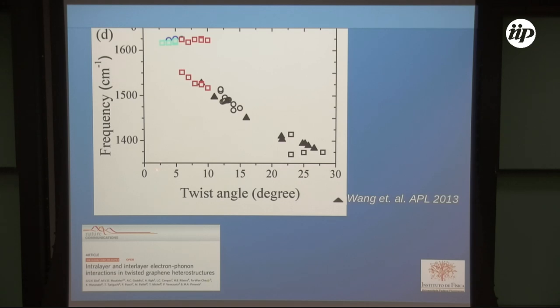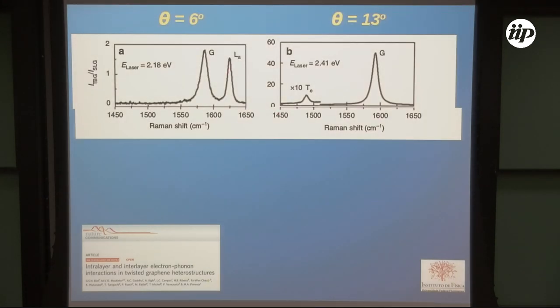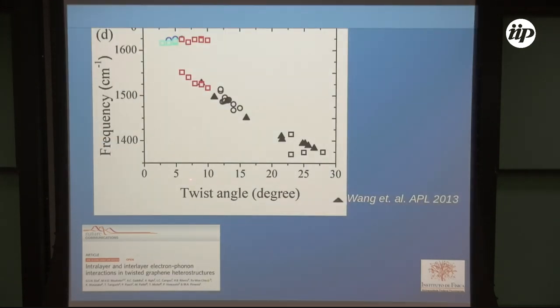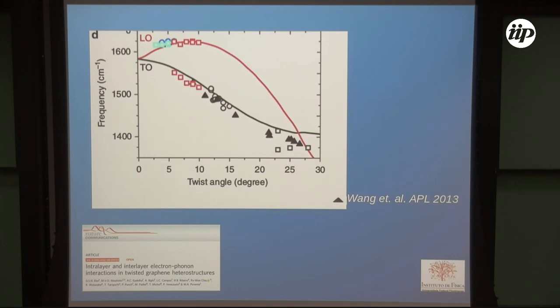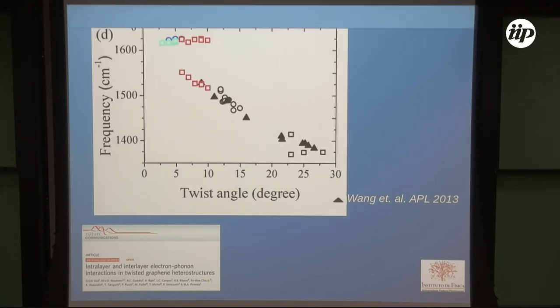So Eliel measured the frequency of these different peaks here, for instance, this one and this one, for several angles, okay? And also here we have some experimental points taken from this work. Okay, so basically, those are all the measurements by Eliel. And now the first thing, how can we imagine that? We can think that when we have a very large unit cell, we will have a folding of the phonons to the gamma point, okay?